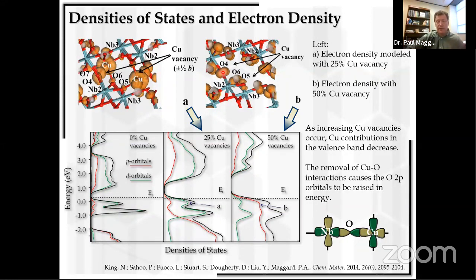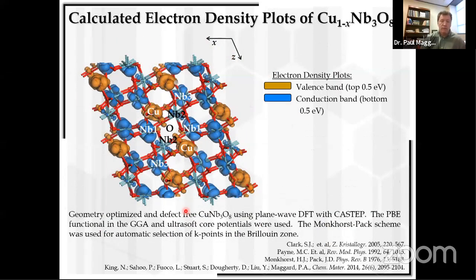And this is important because it leads to a mechanism of more efficient charge separation. Because now wherever there's a copper vacancy, you have the highest oxygen orbitals in your diagram. And wherever you have copper still occurring in your material, not vacant, you have the lowest part of the conduction band. And so if you plot out the electron density of the material, wherever there's copper, you have a very low part of the valence band. So I'm showing you the valence band, the top half eV of it in orange here, and the conduction band, the bottom half eV of it, blue here.